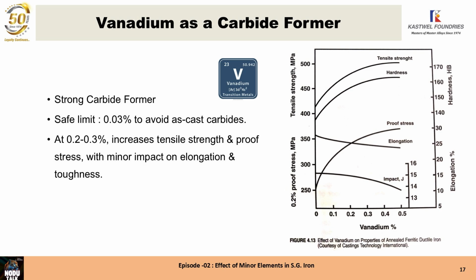Vanadium is another carbide former. It's a very, very strong carbide former. The safe limit for vanadium is 0.03% to avoid as-cast carbides. At 0.2 to 0.3%, as you will see in the graph, vanadium increases the tensile strength, the proof strength, and the hardness, with minor impact on elongation and toughness. So vanadium is to be avoided. It is used in some steels to improve weldability. But vanadium is a poison as far as SG iron is concerned because the carbides are very, very strong.